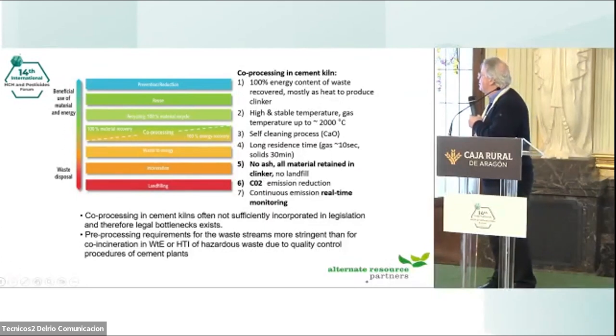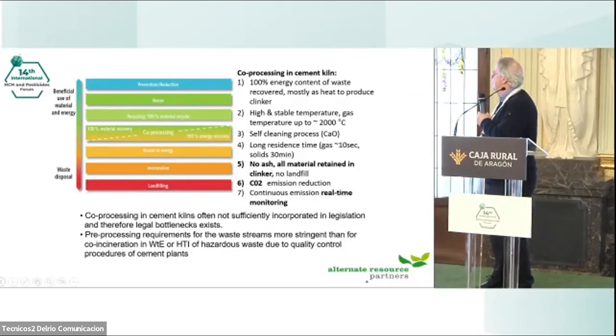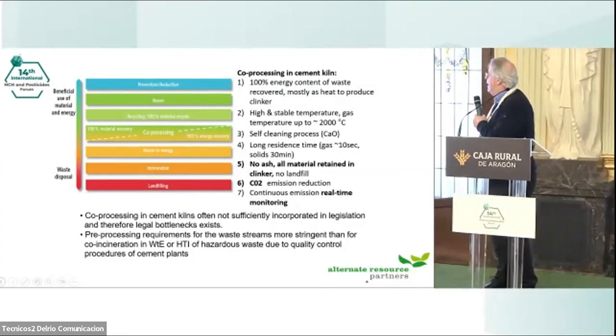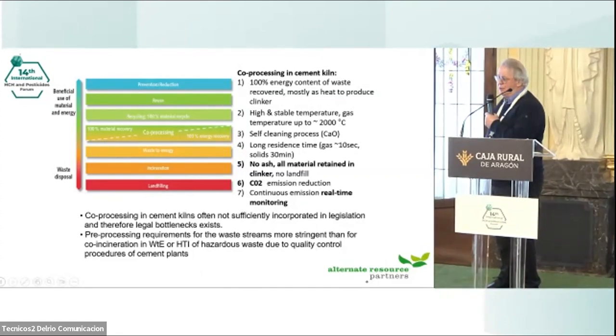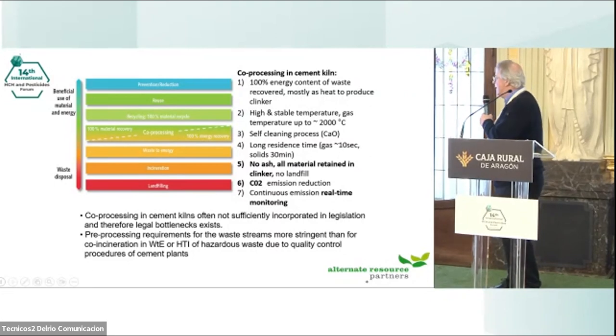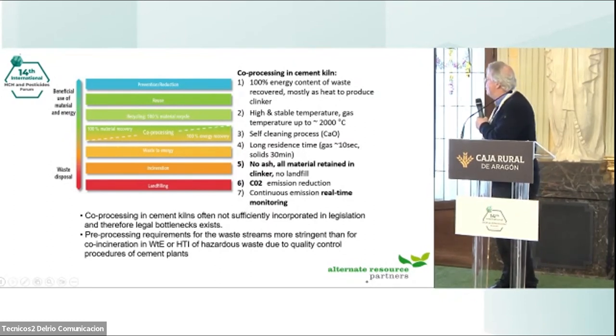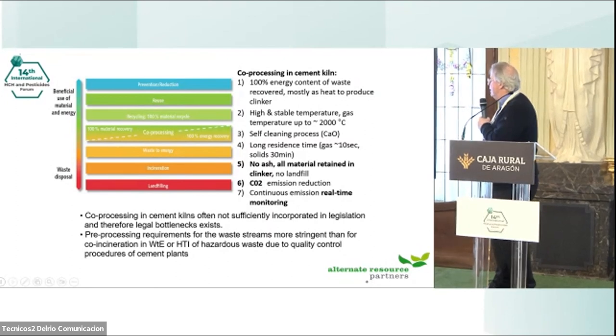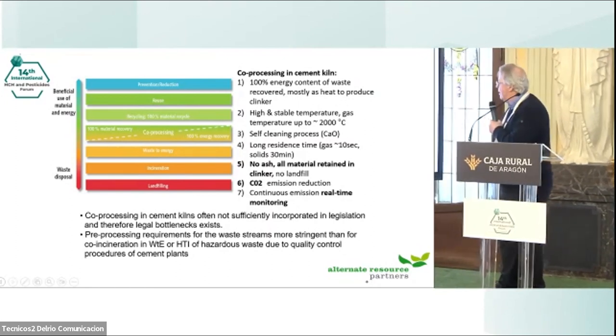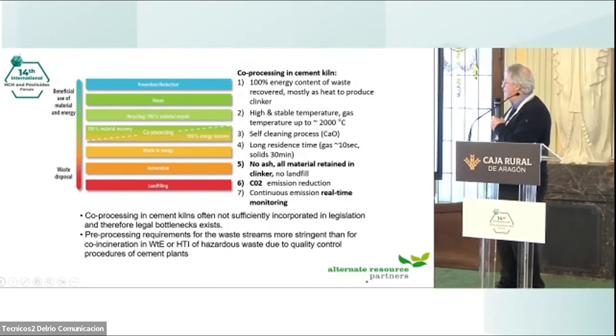We have a high and stable temperature, up to 2000 degrees on the gas temperature and 1400 degrees on the material temperature. It's a self-cleaning process because of the calcium oxide, and it has a long residence time, the gas for about 10 seconds and the solids for about 30 minutes. There is no ash, all material is retained in the clinker, so there is no landfill for it.